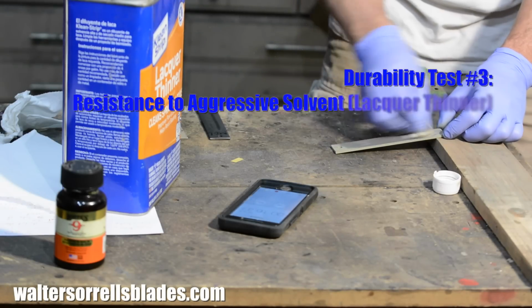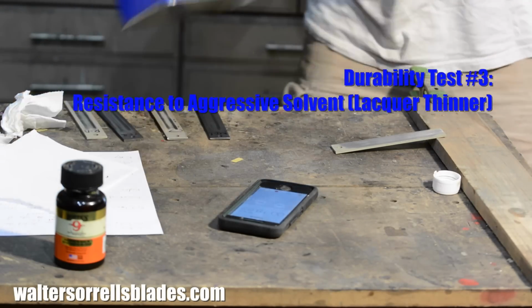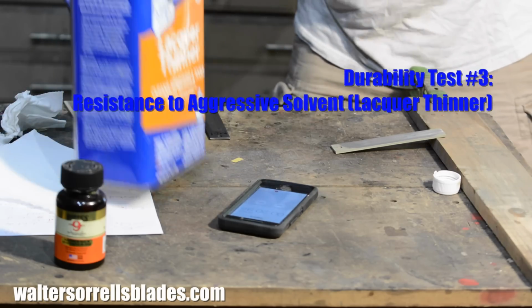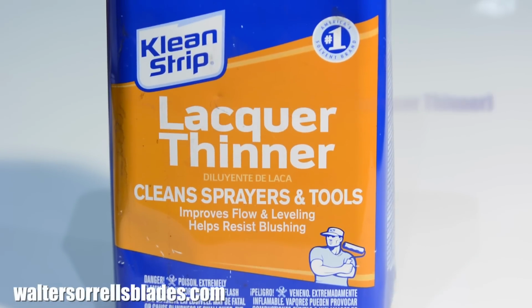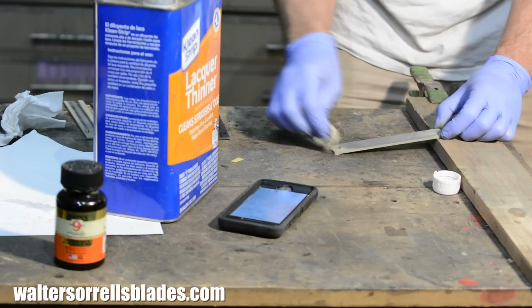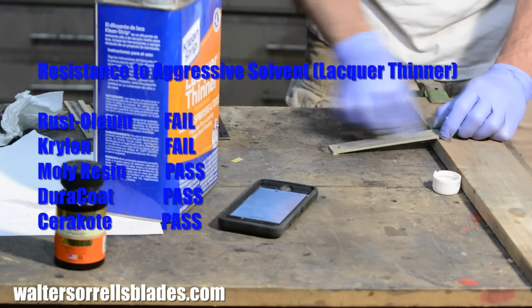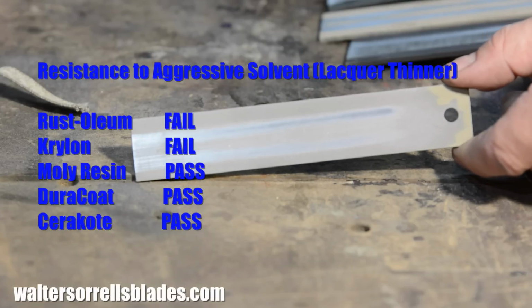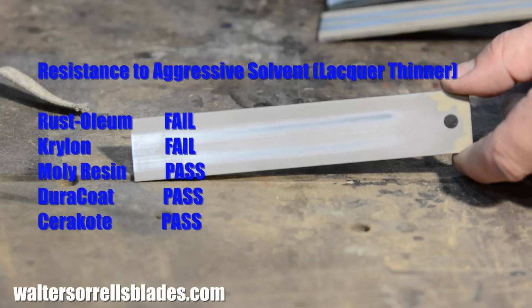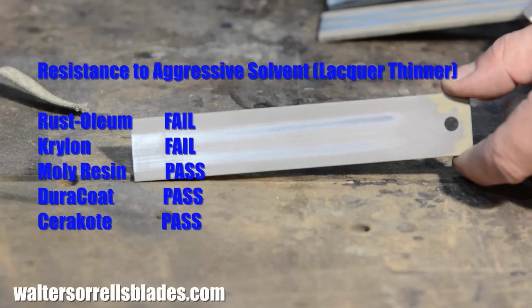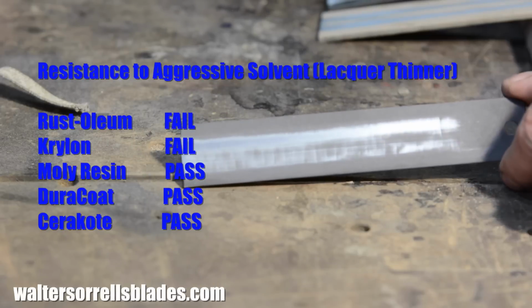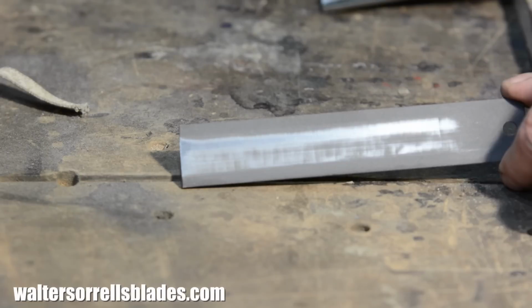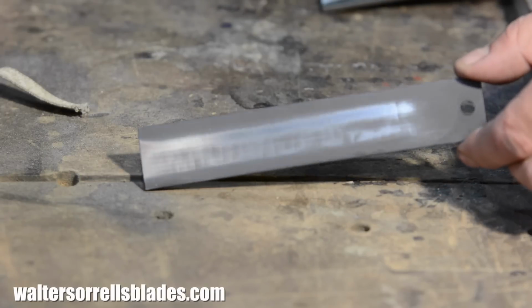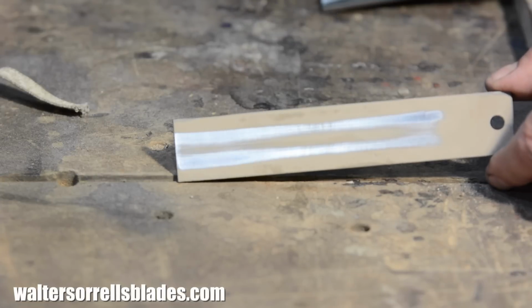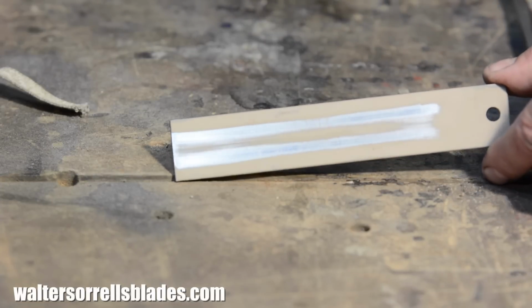Third, this mirrored test 2, but using a much more aggressive solvent, lacquer thinner. The paint disappeared like the tears of a virgin in a Saudi Arabian sandstorm. The resin-type products, on the other hand, Moly Resin, Cerakote, and DuraCoat, were completely impervious. So, if you plan to dunk your firearm or knife into industrial solvents, don't go with either of the paints. At least as far as this test could determine, Cerakote is the clear durability champion. DuraCoat was second, and the rest were well behind that.